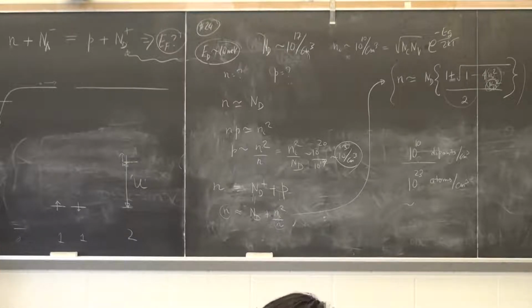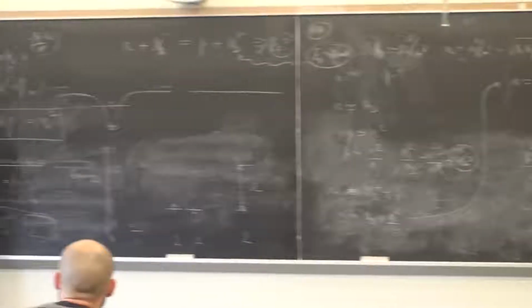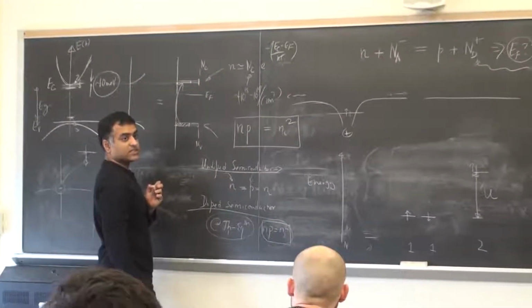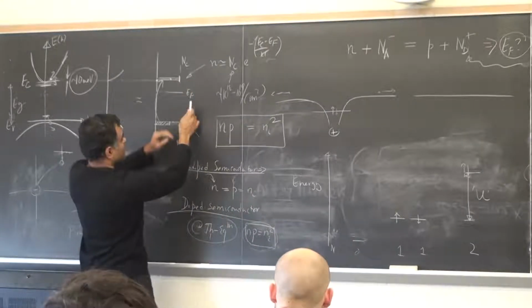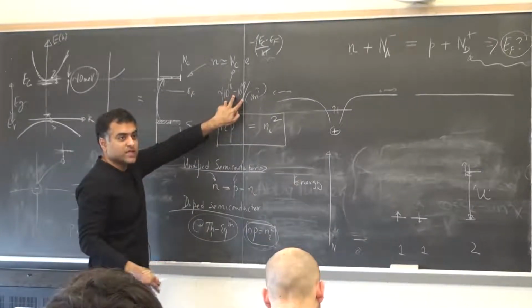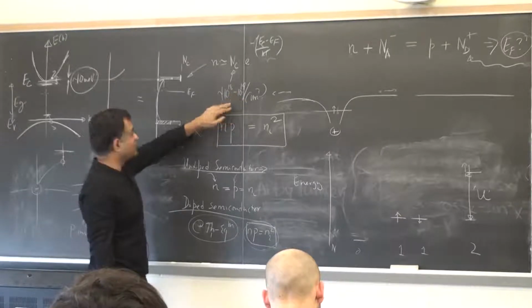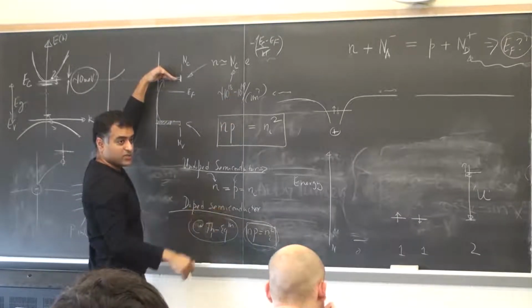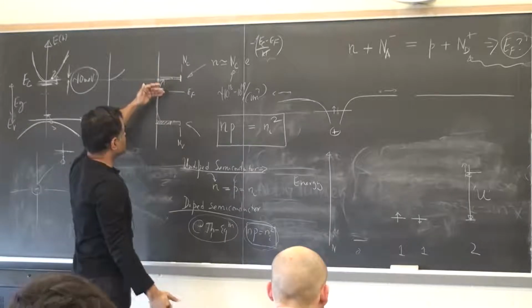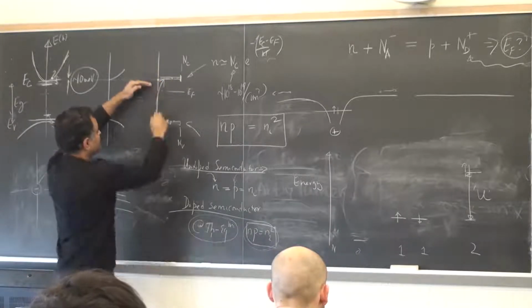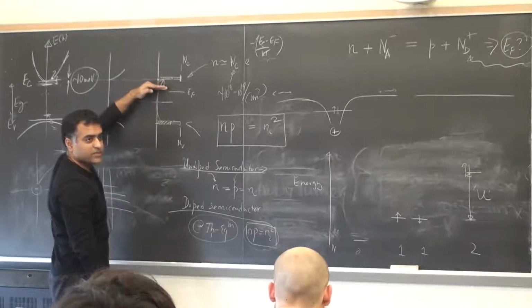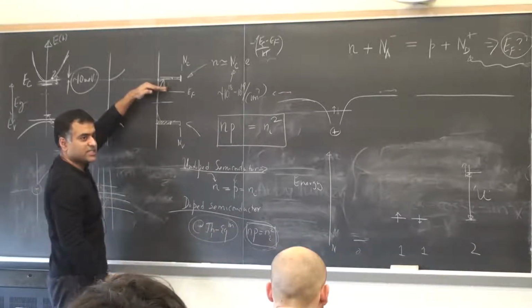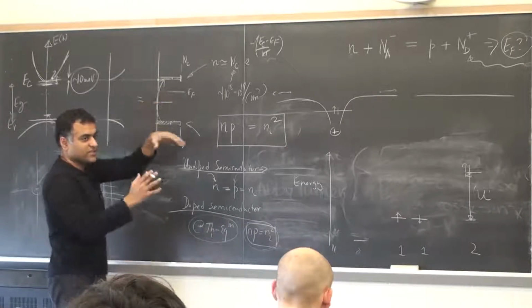Now when we say heavily or lightly doped, it is when your doping density becomes of the order of the band edge density of states. That's heavily doped. For example, 10 to the power 18, 10 to the power 19 is a heavily doped semiconductor, and the Fermi level is almost moving into the band now. Intrinsic would be when it's in the middle roughly. Lightly doped is somewhere up here, maybe 10 to the power 17, 10 to the power 16. That's kind of a small window typically.